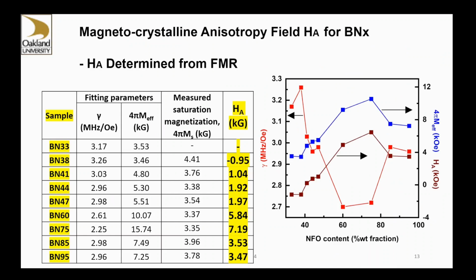And we are able to find the anisotropy field for the composite. These measurements were done in ferromagnetic resonance. Measurements were done on platelets of these composite structures. And what is shown here is the anisotropy field we determined from FMR and static magnetization measurements. Negative sign represents anisotropy perpendicular to the plane, and the positive sign is in-plane anisotropy.